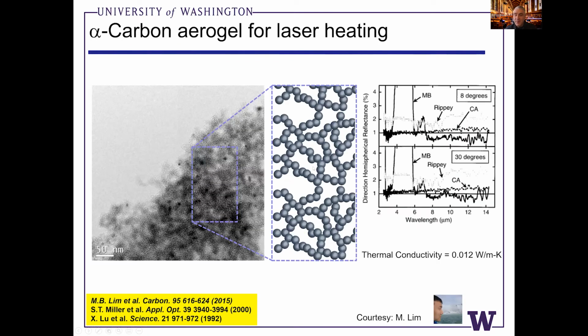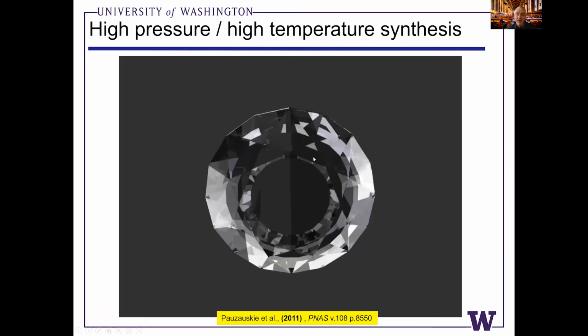And then one property of the aerogel I wanted to point out is that because of its composition of carbon and very high surface area, it has an extremely high optical absorption coefficient. The reflection coefficient in all directions over a very wide wavelength range is effectively zero. It's on the order of 1 or 2%. So it's almost like a black hole that every photon that hits it sticks and can't escape. It also has a really low thermal conductivity because of its sort of mass fractal microstructure. So it really doesn't conduct heat that well. So we can really heat this stuff up to very high temperatures.